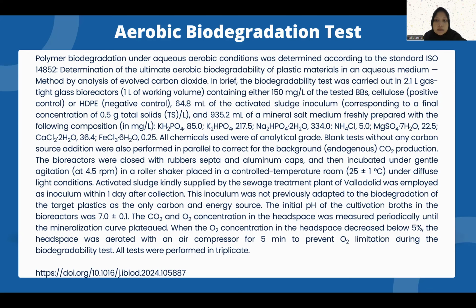In brief, the biodegradability test was carried out in 2.1 liter gas-tight glass bioreactors, 1 liter of working volume, containing either 150 milligrams per liter of the tested BBs, cellulose as positive control, or HDPE as negative control, 64.8 milliliters of the activated sludge inoculum, corresponding to a final concentration of 0.5 grams total solids (TS) per liter, and 935.2 milliliters of mineral salt medium freshly prepared with the following composition in milligrams per liter.